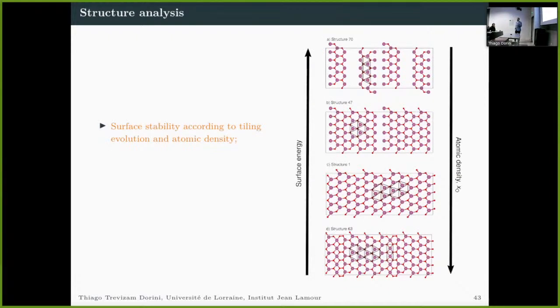So here I've highlighted 4 structures that correspond very well to what's happening to the surface stabilization of these phases. The least stable structure, as you can see on the top, has only this tiny hexagonal configuration, with a lot of holes in the structure. When you decrease the number of holes, you stabilize the surface free energy. When you remove all the holes, you stabilize even more, but in this case the hexagons become a bit distorted. And when you combine the hexagons with the rectangular tiling, you have the most compact oxide structure, and this leads to a more stable surface free energy for these oxides. And this approach can be used for all the other oxides that we have studied.